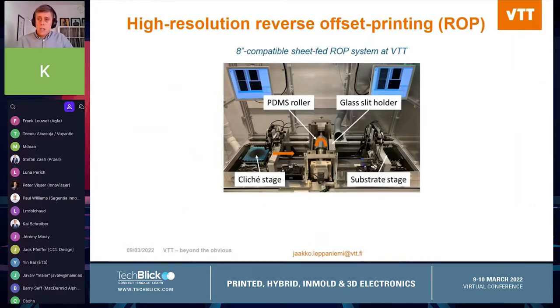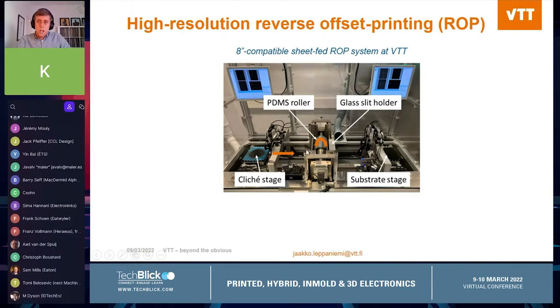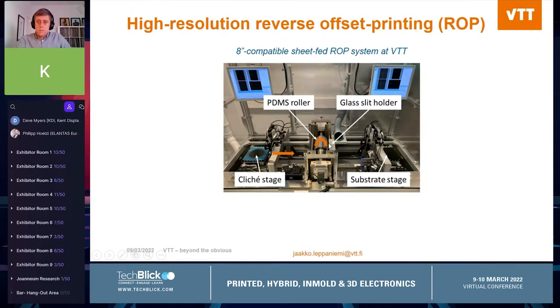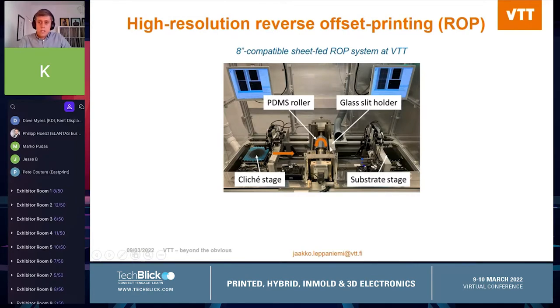We have been working on a high resolution printing method called reverse offset printing, or ROP in short. At the center you see our new 8-inch compatible sheet-fed reverse offset printing system. This ROP method is based on three main steps: coating, off, and set steps. First, ink is coated on the top of a PDMS roller, where the ink is let to reach semi-dry state by partial absorption of the ink to the PDMS and evaporation. And the ink has high cohesion and viscosity in this semi-dry state.